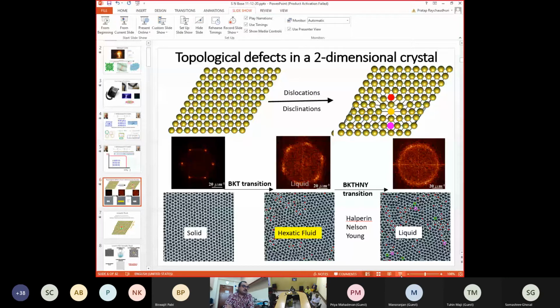So if you do the Fourier transform of this, which is the same as doing a diffraction experiment, you get 6 sharp spots here. Here you can see those spots have become extremely wide, but still the 6-fold symmetry remains. That implies that you have not lost the orientational order. Soon it was understood that what is destroyed in this phase transition is the positional order, which means that if I know the position of a vortex here, I can no longer predict the position of a vortex far away. But the orientational order remains, which means that if I know the bond orientation at some point here, I can approximately predict the bond orientation of a bond that is far away within an inaccuracy that is less than 60 degrees.